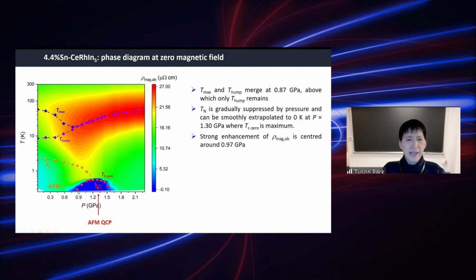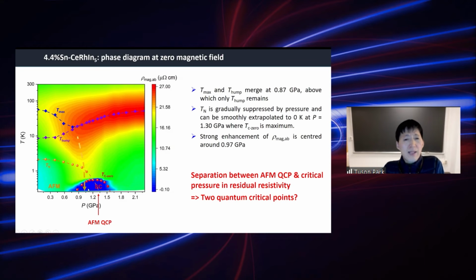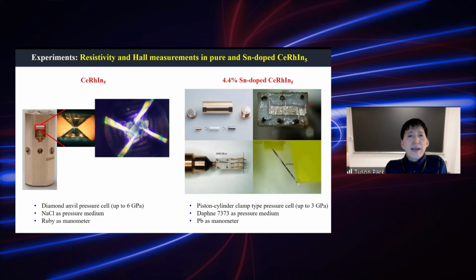Then the dome of superconductivity occurs around this AFM QCP point. However, the enhanced magnetic resistivity does not end here, but rather has anomalous behavior well within the antiferromagnetic state, suggesting that there may not be just one critical point, maybe two critical points. Okay, so in order to address this issue, we performed experiments on both the pure compound and the 4.4% tin-doped CeRhIn5 compound.